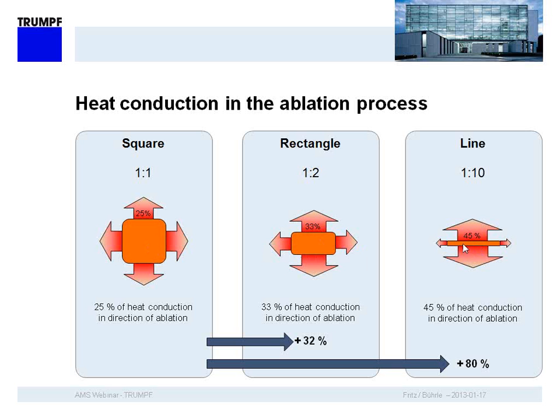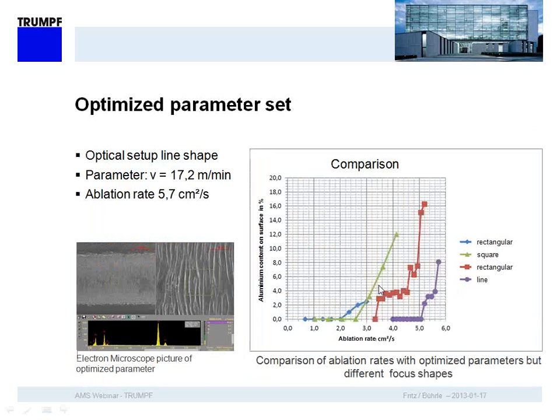That means if you do that, you also have to do overlaps, and you are bringing much more energy per square millimeter surface. And to not slow down the process, because you have a much smaller surface, you have to increase frequency. And it was interesting that our laser is the only one that can really do that job. So here on that comparison sheet, we did many trials. I just want to show it in this graph. And the result with that line laser was outstanding.